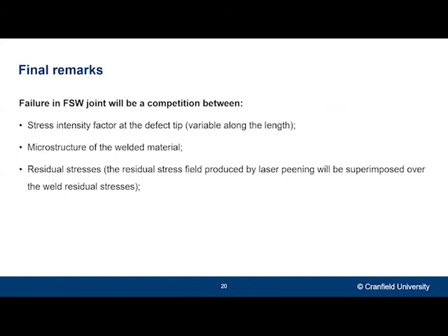So to wrap up all of that information, the main conclusion that I wanted to share is that so far this project has allowed me to conclude that the failure in friction stir welded joints will be a competition between three main factors. The first one being the stress intensity factor at the defect tip, which is variable along the length and also depends on the geometry of the defect. Secondly is the microstructure of the material. And finally, and probably the most important, the residual stresses, both the residual stresses that come from the welding process alone and the residual stresses that come from the peening treatment, which will superimpose with those initial residual stresses.